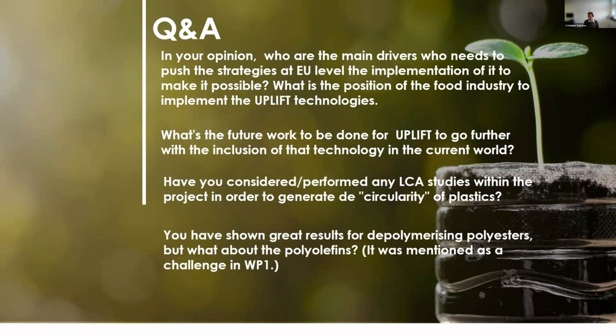And this is why we changed strategy, going from just microbial depolymerization into the valorization and upcycling of the pyrolysis wax. So combining basically the chemical recycling of polyolefins, taking the side stream, which is this pyrolysis wax, and upcycle that. And there we've seen actually quite promising results because these processes are quite fast. We saw that within basically 20 hours, 90% of the polyolefins were converted.